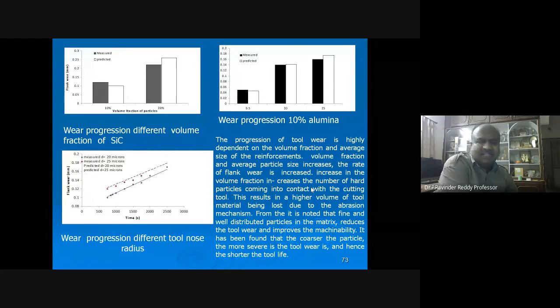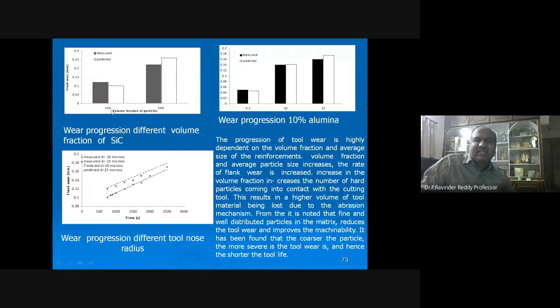When you discuss these results, the wear progression, different volume fraction of silicon carbide. So volume fraction on the x-axis, you have 10% and 20%. Then we have a measured one and a predicted one. So flank wear in mm, you can observe the measured one. When volume fraction is increasing, it is increasing, in both measured and predicted.